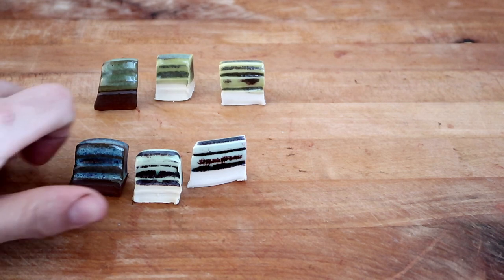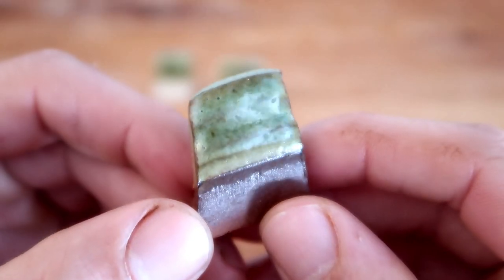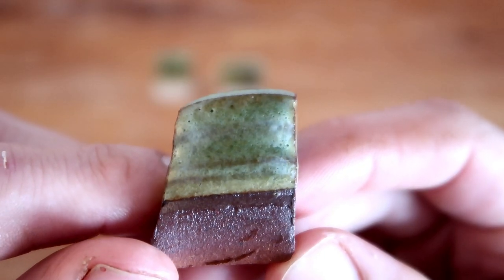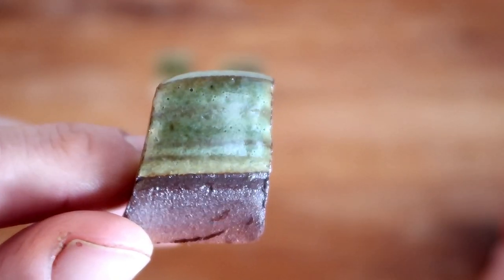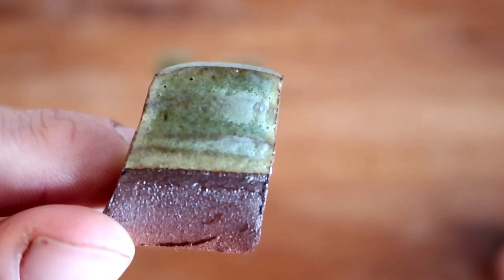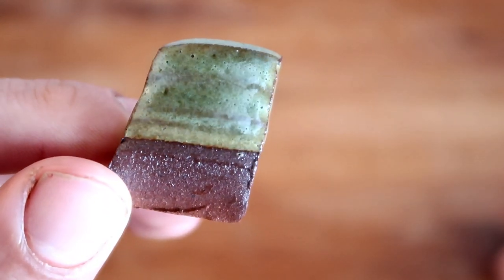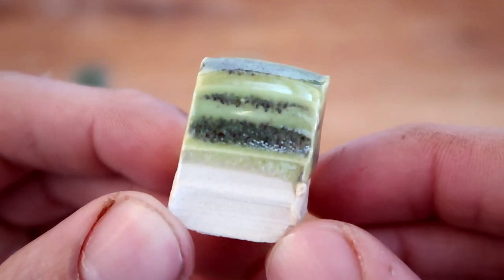Okay, let's take a look at the second glaze recipe. Let's take a look at the brown test tile first. I like the green a lot on the redstone test tile, but it's kind of a basic green — it just looks super normal to me. I really think I put this glaze on too thick because I'm seeing one or two pits on every test tile. When I check the notes in the glaze recipe book and on John Britt's Instagram, he says do two very quick dips if you're looking for the best results — I just did it way too long.